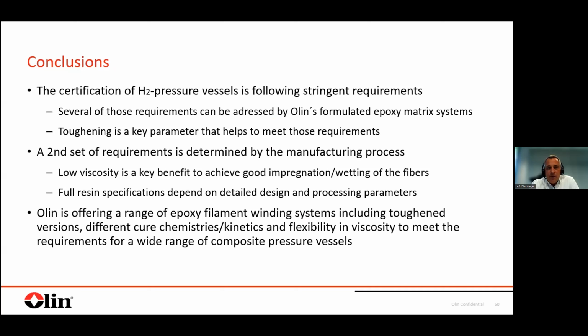And the second set of requirements is determined by the manufacturing process. And this is really where low viscosity is a key benefit to achieve a good quality and stable and reliable wetting of the fibers. But on the other hand, we have seen that the full resin specification depends on a lot of details of the design and processing requirements, where you always need to find this balance between the different requirements. So we are offering a range of filament winding systems, including toughening, including different cure chemistries and cure kinetics, and with flexibility on viscosity.